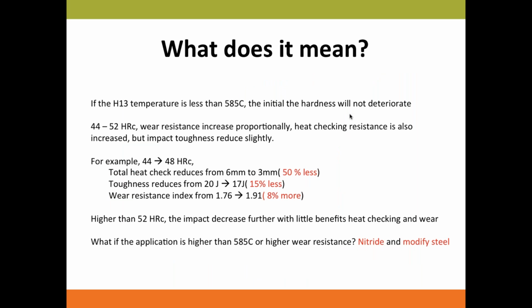So what does that mean to us, the die caster? As long as the temperature is lower than 585 degrees Celsius, what you put in, you should expect you will get from it. Let's say if you put in 44 Rockwell to start, it should last up to 585, still have 44 Rockwell and doing the job for you. And from 44 Rockwell to 48 Rockwell, we can see the heat checking reduced by 50% from 6 millimeter to 3 millimeter, but the toughness reduced a little bit less, from 20 to 17, and wear resistance increased even less, only 8%.